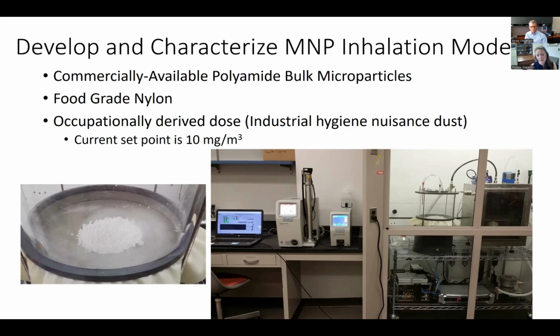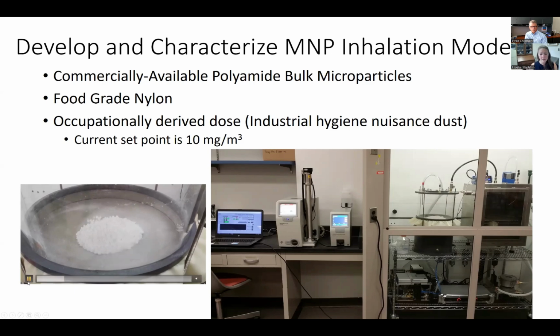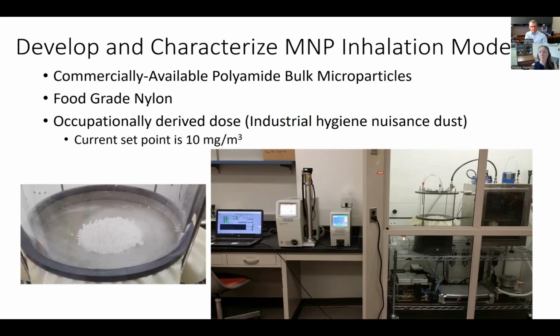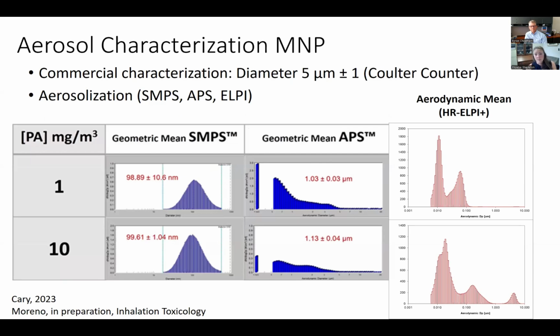So we aerosolize our particles here. We use an acoustic generator to aerosolize them and put them in the air. There are many different components measured in real time to understand the dose, the temperature, and the humidity within our inhalation chamber. The animals sit in our inhalation facility, they fall asleep, and they breathe in these particles. We were able to characterize them with our techniques. The commercial characterization identified these particles as having a diameter of 5 microns, with an error of about 1. So this is well within that microparticle range. And when we aerosolize those, the smallest particles get lifted into the air.